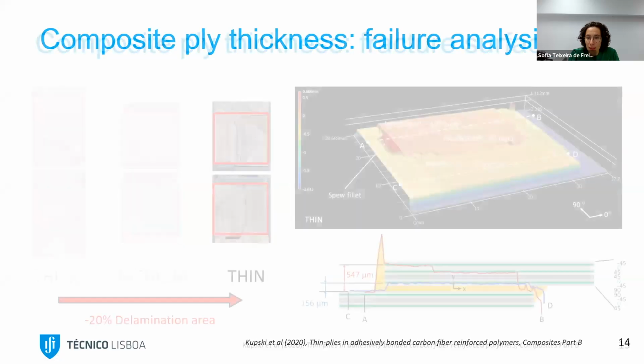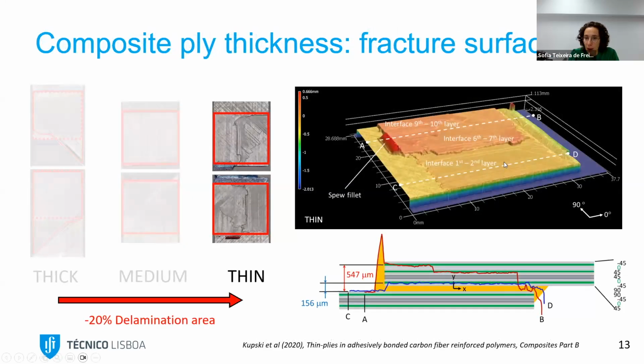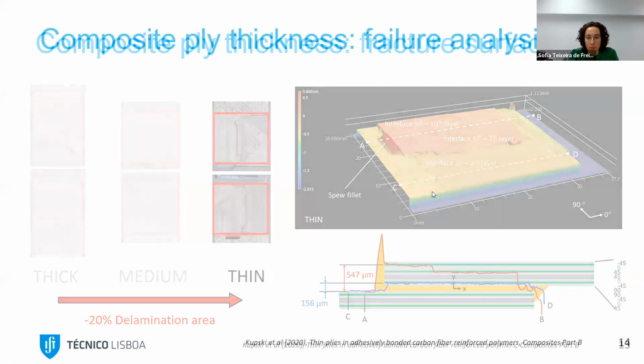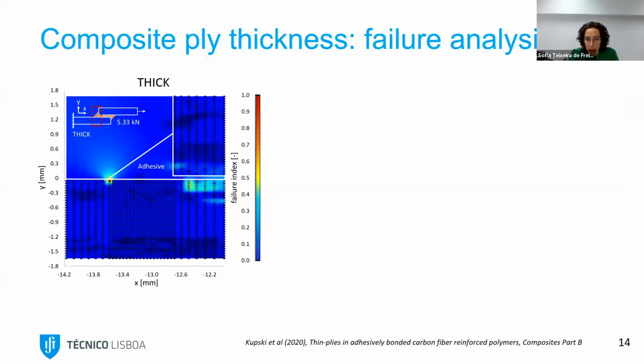Now, in order to understand better why this is happening, why we have on the thick only one quite flat crack path, and here we had a stepwise crack path, we performed a finite element analysis to try to understand where the crack is initiating. So here what we see is a zoom in of this region of the bonded joint, closer to the edge and the fillet, which is normally the hot spots where the stress concentrations happen.